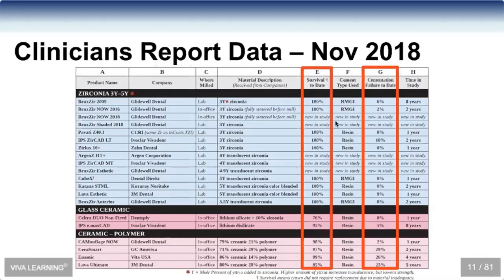If you just glance at the zirconias here, not all of them have been in for 8 years. You can see a lot of them have just been in for 1 and 2 years, but they're all at 100%. So again, that higher strength of zirconia is being shown clinically to be true as well. But if we come down here to glass ceramics in this dark pink column, here's IPS Emax, and you can see that its survival is also 8 years. It and BruxZir were launched at the same time in this study by Rella, at 95% survival rate. That's pretty amazing, and only 5% cementation failures there as well.